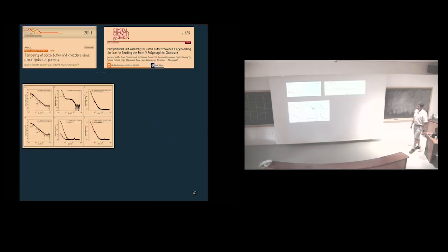We have also looked at other things that affect crystallization. In this NatCom paper, we actually added phospholipids or lecithin that, believe it or not, is not only the fat. The minor components that are in there, like phospholipids, free fatty acids, and other mess, affect the crystallization and polymorphism. And we found out that certain phospholipids form reverse micelles in the melt, and then they associate with the crystal, and we could actually get to a stable polymorphic form without tempering. So we didn't have to do the whole tempering regime. We just do something very simple, cooling and heating, and we can get to the correct crystal form.